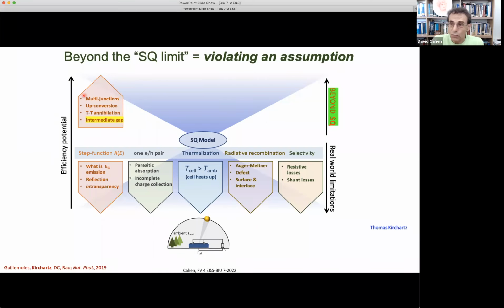Then there's the possibility of what's called upconversion. I can take two photons and make them into one. This happens in nonlinear materials, only at rather high intensities, and therefore was never considered practical. But in the last decade and a half, triplet annihilation has shown that it might actually become practical. And this is something that happens in organics.